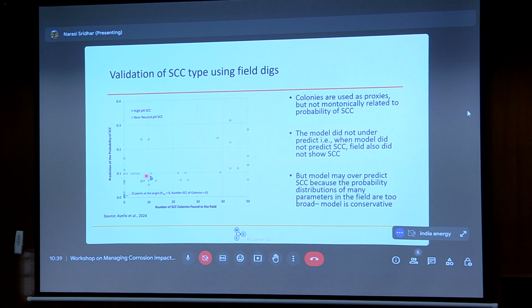So here is just a brief slide of the validation. What we did was compare the number of SCC colonies found in the field versus predicted probability. And you can see there are 32 points in the field that showed no SCC, and the model predicted that there will be no SCC. The model did predict there will be SCC when there was no SCC, which is okay. It's a bit of an over-conservative approach. But wherever there was SCC in the field, the model was able to predict the right type of SCC. So that gives us a comfortable feeling that we have captured all these diverse sources of knowledge and disciplines in modeling this complex problem.